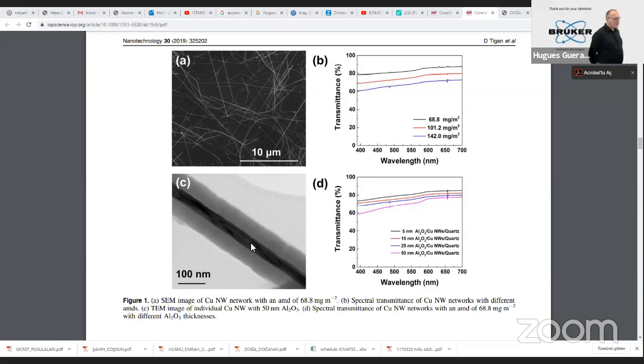No, I think there is no problem. You can use the same technique. So here, what you want is actually to focus really on the wires. You want to try to avoid the single crystal signal. Of course, you should be pretty unlucky to catch it if you do a symmetric scan, because you probably have only one reflection. But if you catch it, that will just cover the whole diffraction pattern compared to this very small intensity.